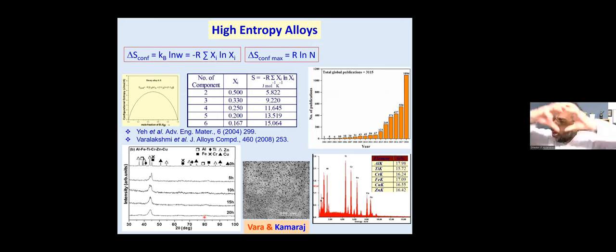So all these elements have different crystal structures. I have aluminum here, which has FCC structure, iron, BCC structure, titanium, HCP structure, chromium, which has a BCC structure, zinc is HCP, copper is FCC. So I am taking six elements with different crystal structures, but all of them are converging into one single solution, which has a BCC structure.